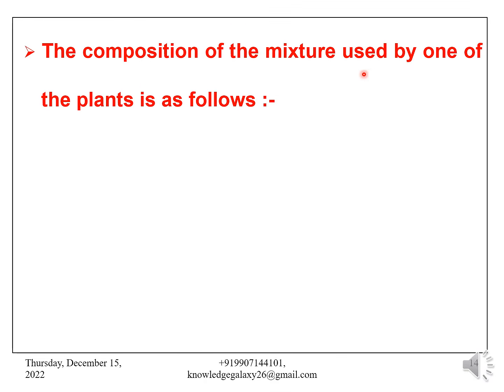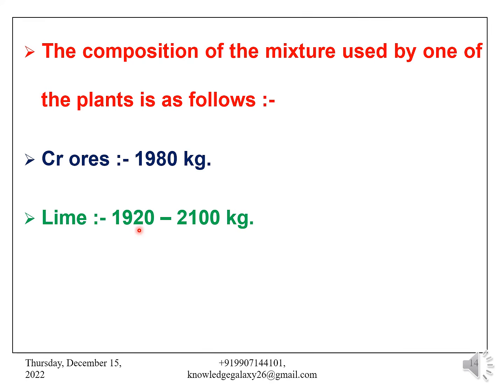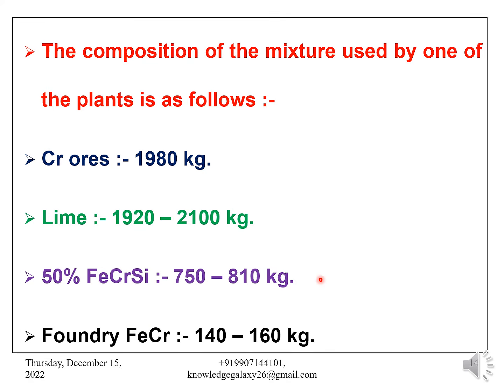The composition of the mixture used by one of the plants is as follows. Chromium ores 1980 kg, lime 1920 to 2100 kg, 50% grade of ferrochrome silicon, so its quantity is 750 to 810 kg, and foundry ferrochrome is 140 to 160 kg.